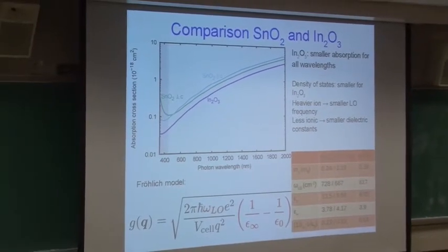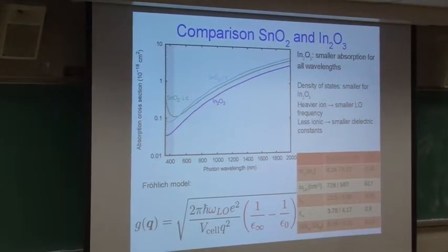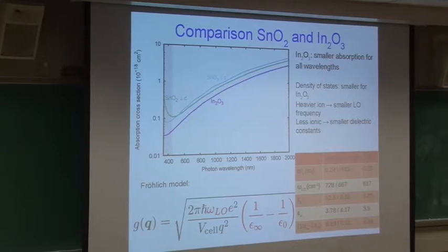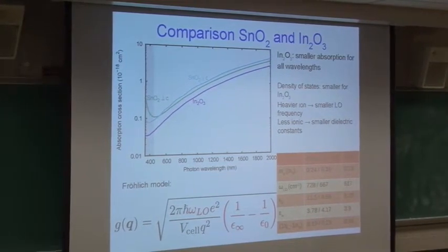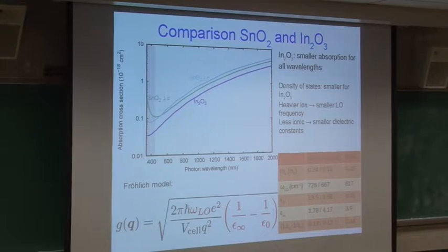At the same time, indium is a much heavier ion than tin. And this means your LO phonon frequencies will be much lower in frequency. And at the same time, because indium oxide is slightly less ionic, you will have smaller dielectric constants.